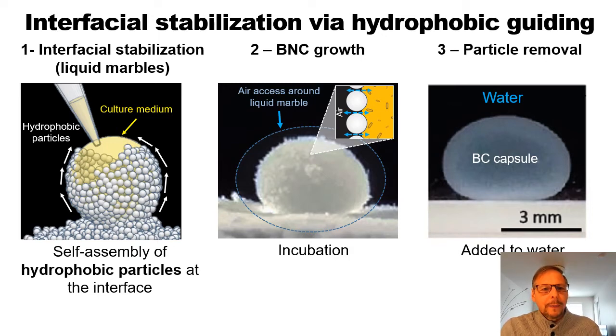In number one, we have a droplet with the culture medium that you can see there in the tip of the pipette. That's the culture medium that we are depositing on a bed of hydrophobic particles. And because of the hydrophobicity, the culture medium that is mostly water will roll up and produce a droplet on the bed of the particles that are hydrophobic. So we're going to get a droplet on the bed of the particles.